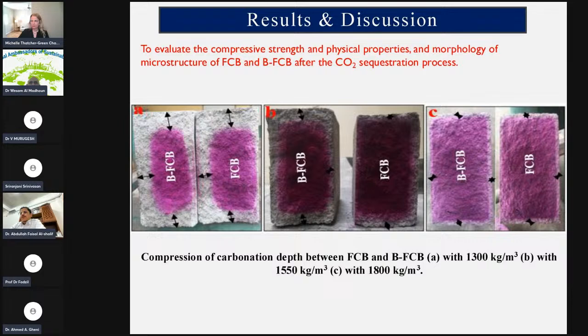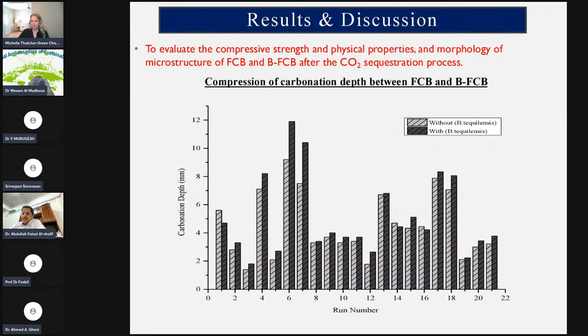Also for this one, if we look at the carbonation with bacteria and without bacteria. Carbonation with the bacteria shows the bacteria absorb CO2 and cause a high depth of carbonation. That's proof that biofoam concrete with bacteria absorbs more than normal foam concrete. That means CO2 was already absorbed by the bacteria. Also, this one is for the carbonation depth. The results show that with bacteria it is high compared to the carbonation depth without bacteria.